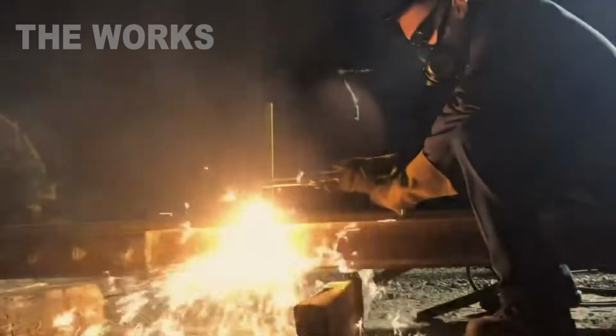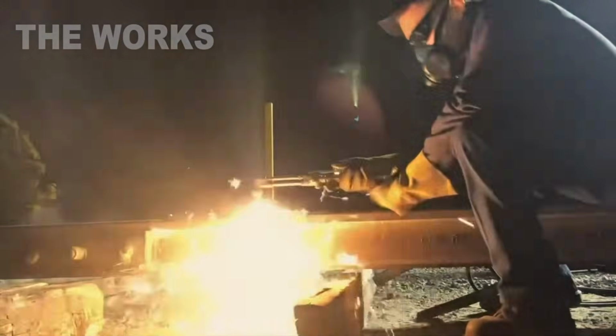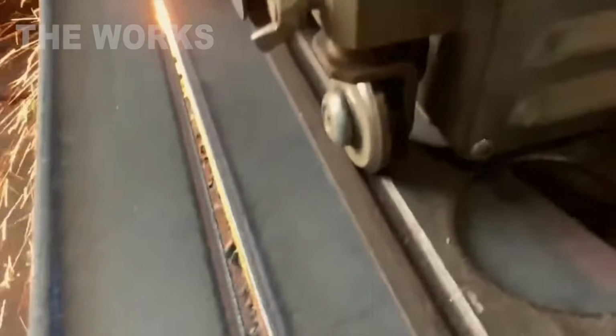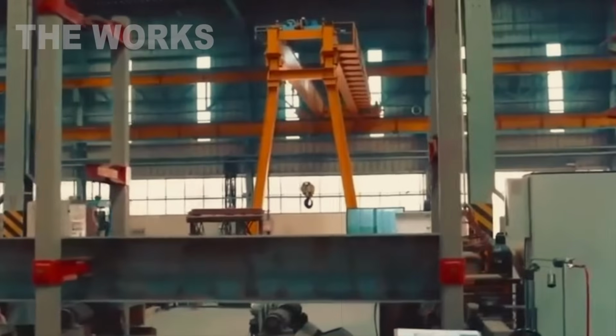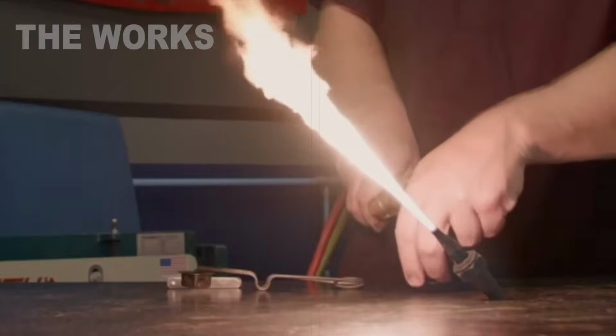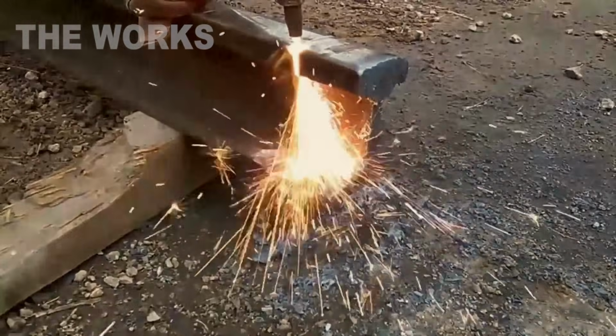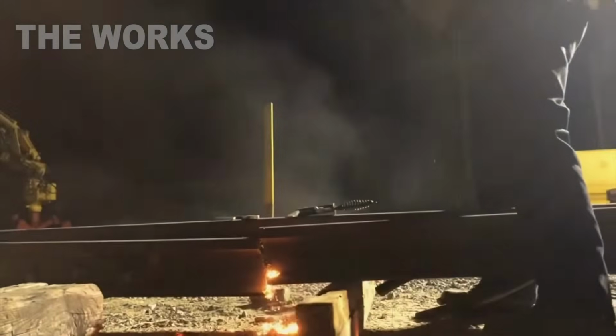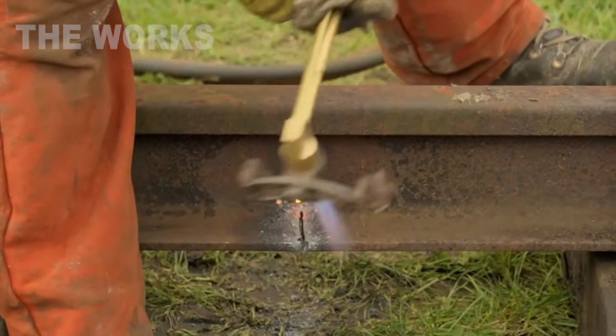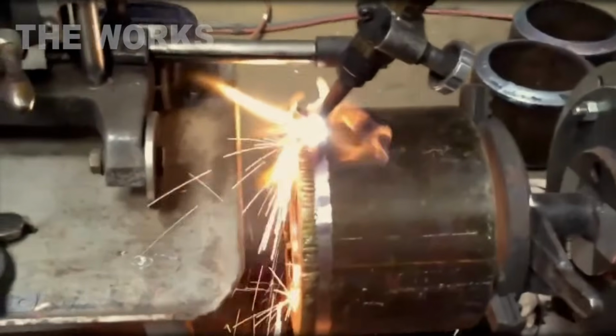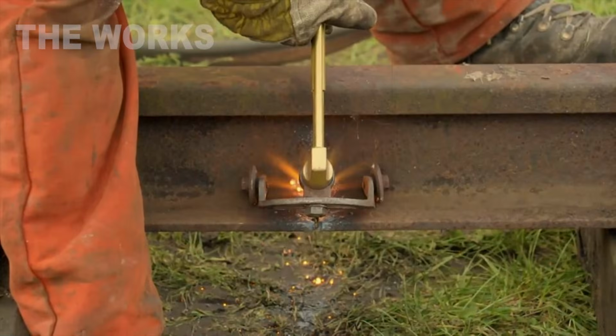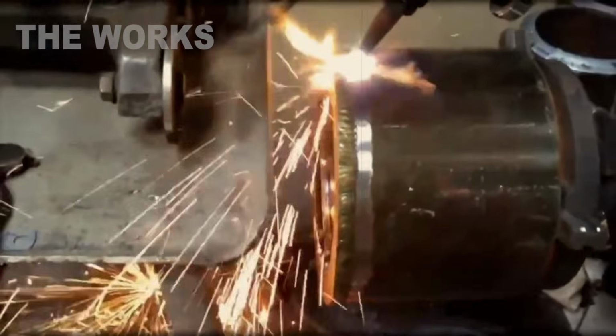Here's the beautiful part. The oxygen doesn't melt the steel, it actually oxidizes it. The steel burns in the oxygen stream, and the force of that oxygen jet blows the molten iron oxide out of the cut, creating the kerf. The operator maintains a specific distance from the workpiece, the gap between the torch tip and the work surface, typically around 1/8 to 1/4 inch. Too close, and the tip will clog with splatter. Too far, and the cut becomes ragged.